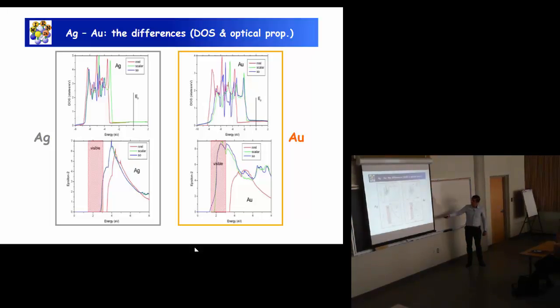And you see that the spin-orbit coupling correction is very small, it will simply change something in this region. So to have yellow gold, you should include the relativistic effect. Or you will have white gold. It is the same for silver. You will have different effects. You see that to have absorption in the visible light, you need to have this relativistic effect.